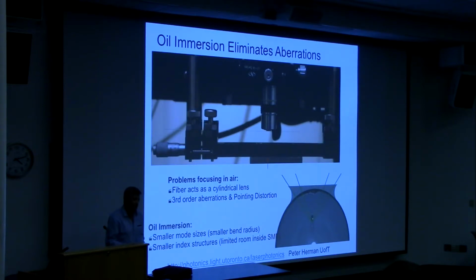And what we need to keep in mind are some of the problems. Firstly, a fiber is a cylindrical shape. So that's astigmatism. When you focus a laser through this, you're going to end up with 2 foci. You're going to get a line focus in X and a line focus in Y. That's a lot different than in the bulk glass. Secondly, when you move the laser left or right, this surface is bending, and so the position you're mapping to is highly distorted. And so the overall interaction is really terrible, especially when you're not focused at the center. There's an asymmetry there, but when you want to write in different places, these distortions prevent this from working.